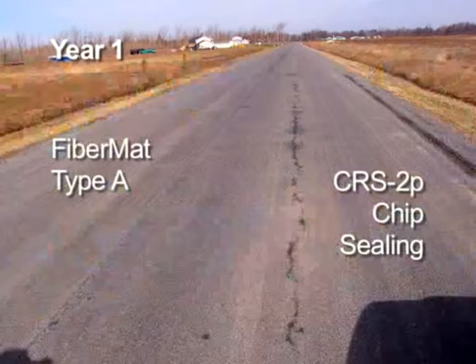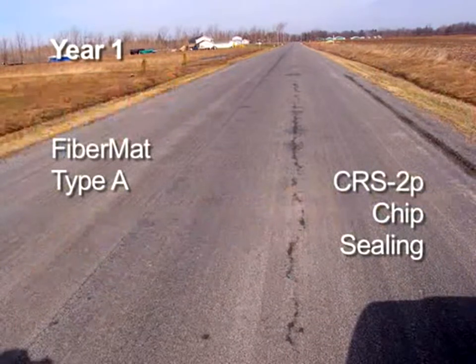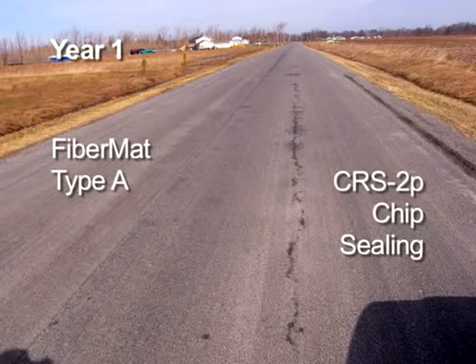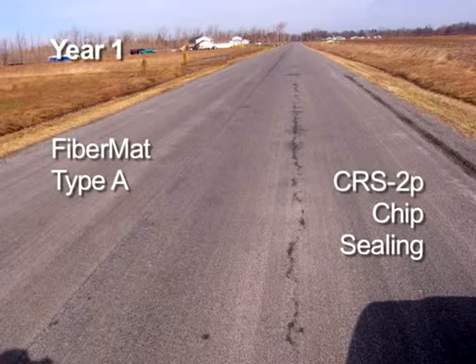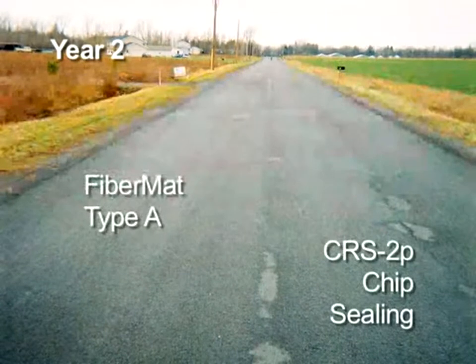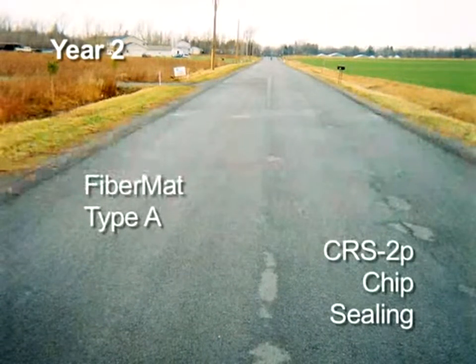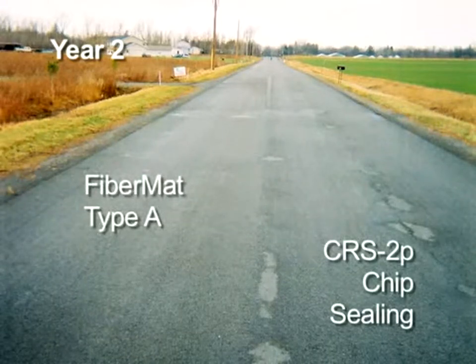After the first 6 months, longitudinal reflective cracks had started to reappear on the regular chip seal side, while no cracks had appeared on the FiberMat side of the roadway. In January 2005, longitudinal reflective cracking and snowplow damage, scalping of the aggregate layer, were evident on the chip seal side, while the FiberMat side was still in very good condition.